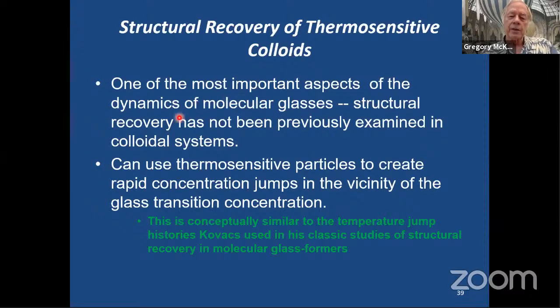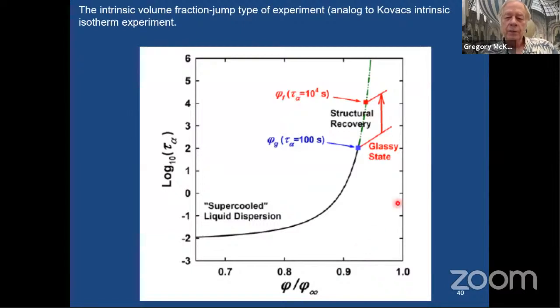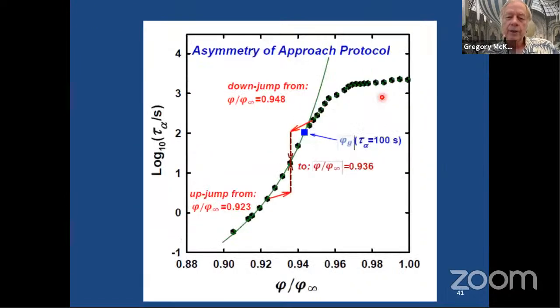One of the most important aspects of the dynamics of molecular glasses, the structural recovery, has not been previously examined in colloidal systems. And so can we use thermosensitive particles to create rapid concentration jumps in the vicinity of the glass transition concentration? And as I said, this is conceptually similar to the temperature jump histories Kovacs used in his classic studies of structural recovery in molecular glass formers. So what we would look at, we could do a jump in concentration or change in concentration and watch it age. We could do an asymmetry. It just shows how you would do it in concentration space, and then watch the dynamics.